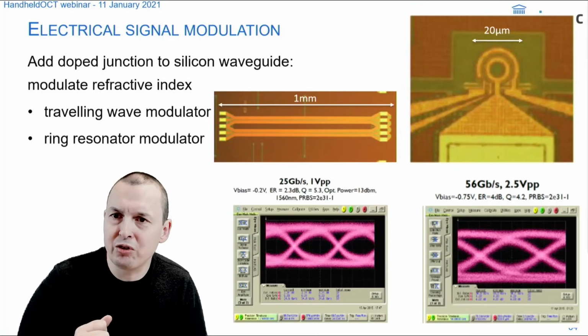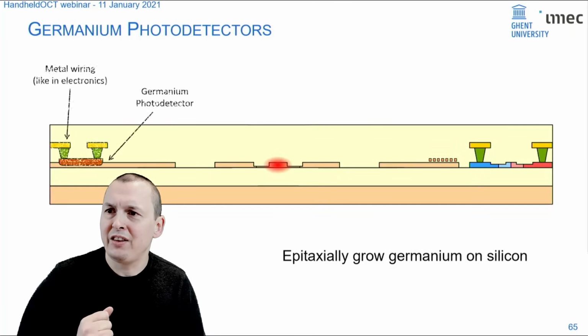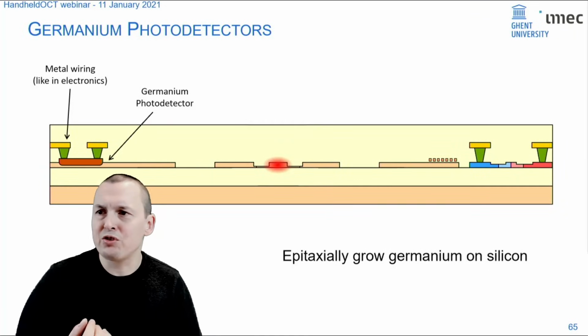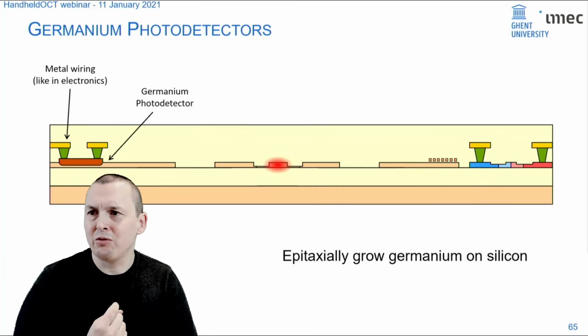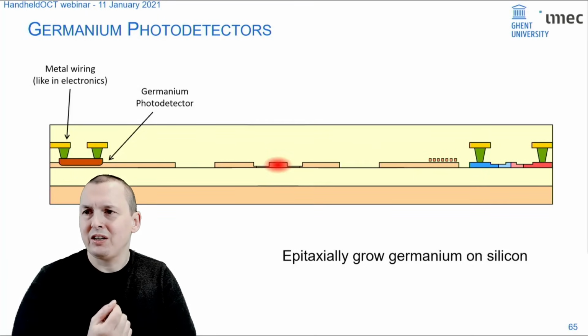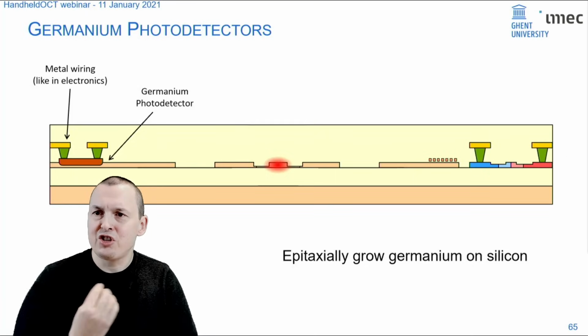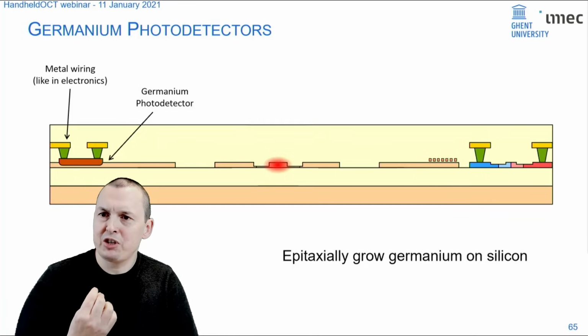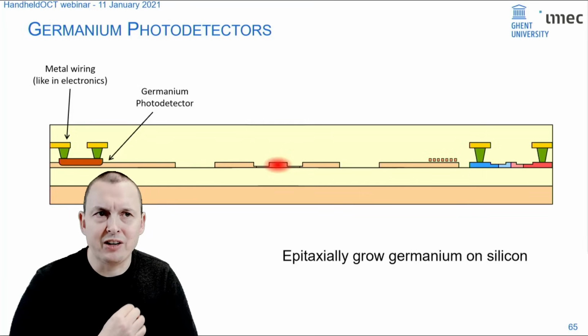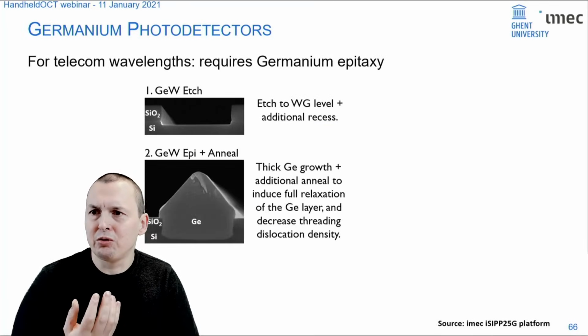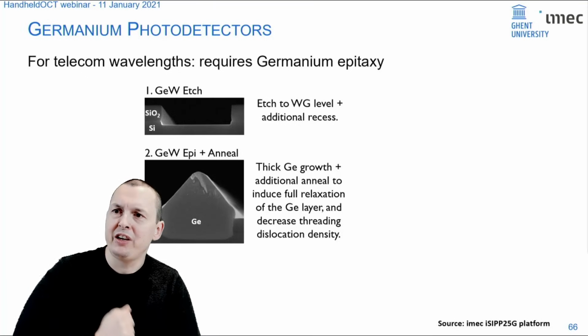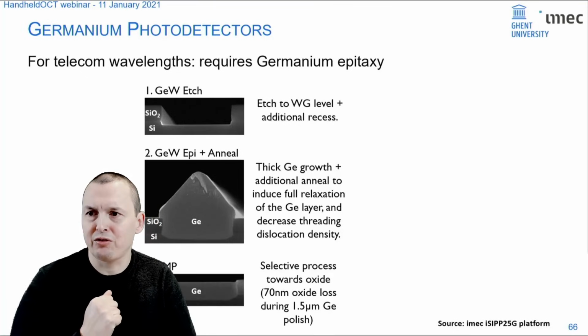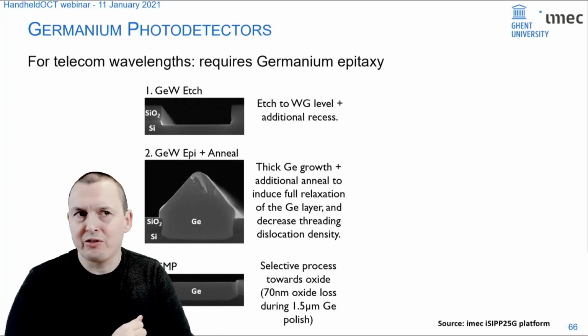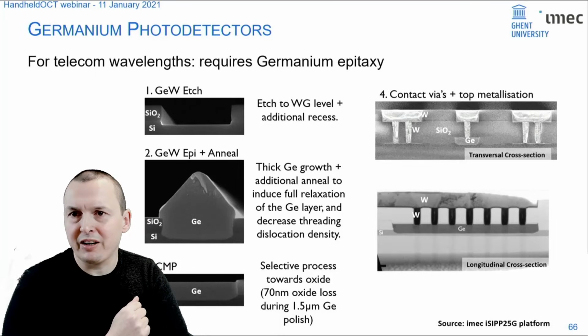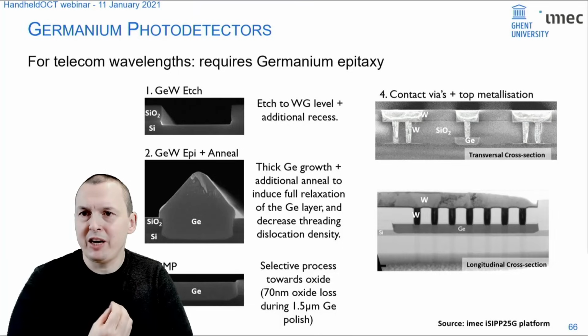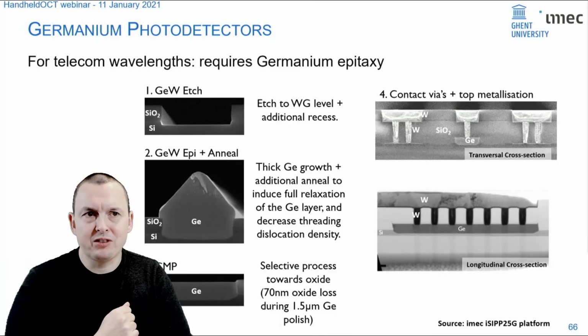Now, if you want to do modulation, you can use these carriers. If you want to do detection, you also have to come up with some new trick. And there, the trick is to do epitaxially grown germanium into your silicon photonics. So you basically grow a germanium layer on your silicon photonics. The germanium has a much smaller band gap in energy, which means it absorbs these telecom wavelengths very nicely. But of course, you need to go through a process where you have a very high quality epitaxial growth of germanium, which is not that trivial. So it took some time to develop this kind of process. As a result, you see cross sections like this, where you have a germanium which is properly contacted with the metals.